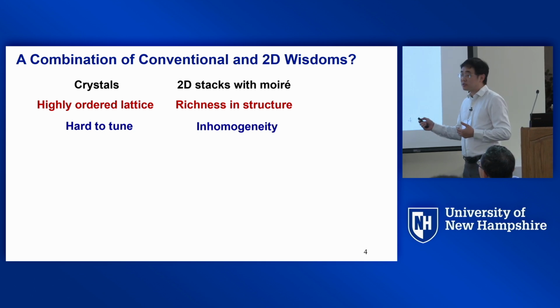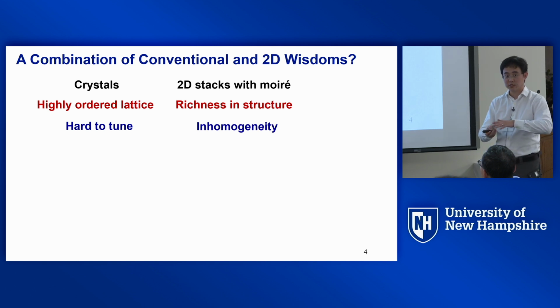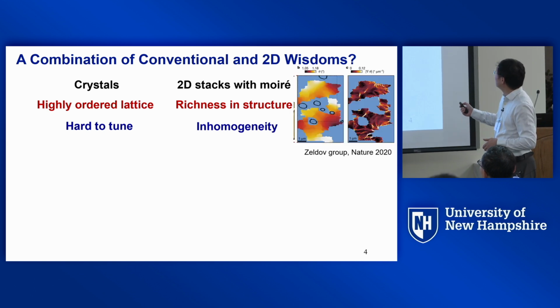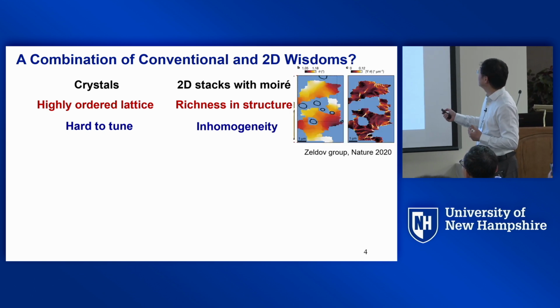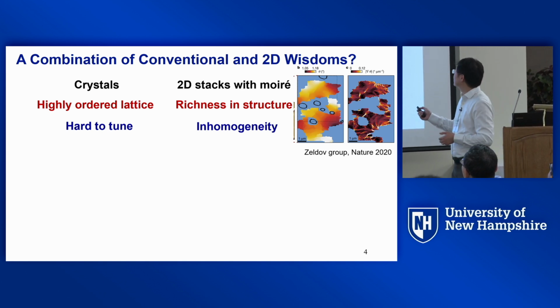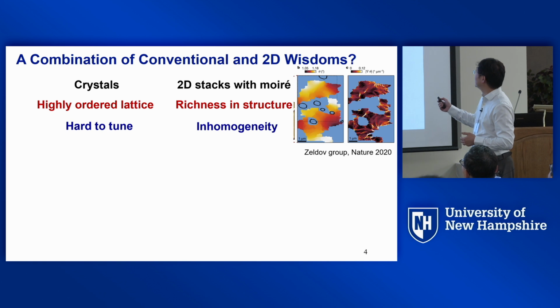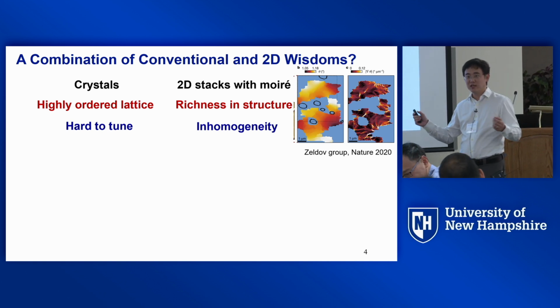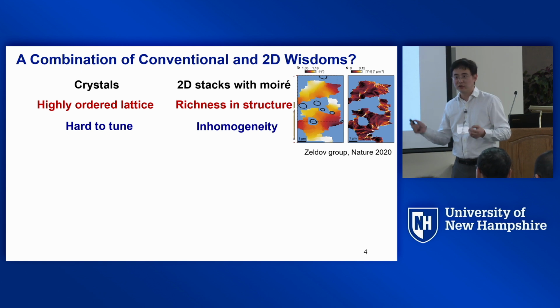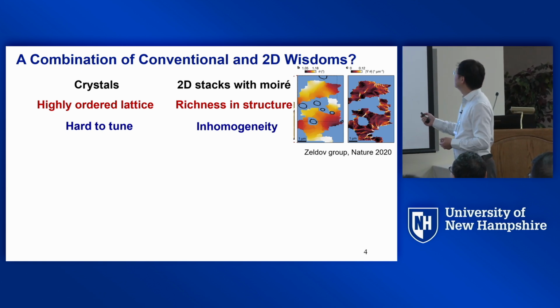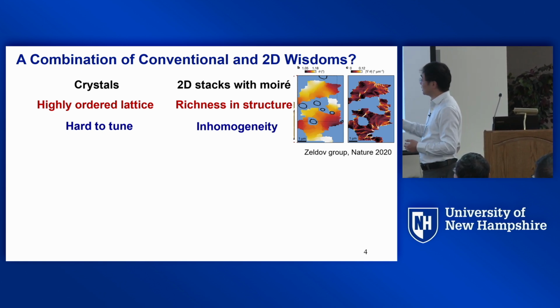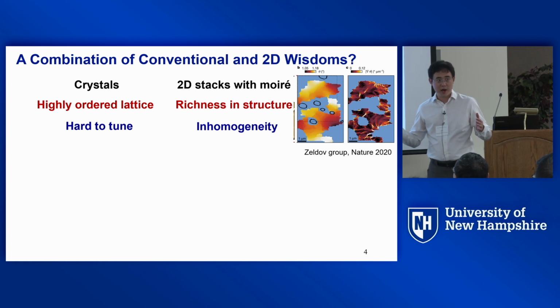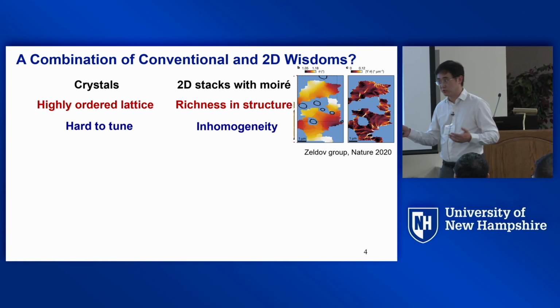But sometimes it has inhomogeneity, especially when you have Moiré between two layers of the same kind. So in the twisted bilayer graphene system, Zeldov's group has used a nanoSQUID probe to visualize the variation of the twist angle. And it turns out, because the angle is magic, if you are slightly off the magic angle, you lose the magic. So microscopically, the properties across this twisted bilayer graphene are actually not that homogeneous.